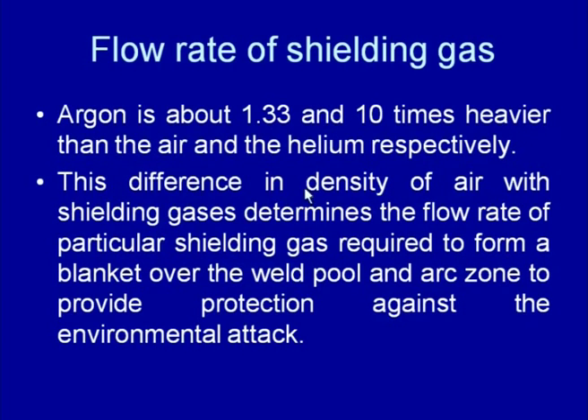The difference in the density of air and the shielding gases determines the flow rate of the particular shielding gas required to form a blanket over the weld pool and the arc zone to provide protection against environmental attack. If the gases coming out of the nozzle are heavier than air, they will tend to settle down all around the weld pool and provide effective protection against atmospheric contamination. But if they are lighter, they will tend to move up immediately after coming out of the nozzle, and will be less effective in protecting the weld pool from atmospheric contamination.